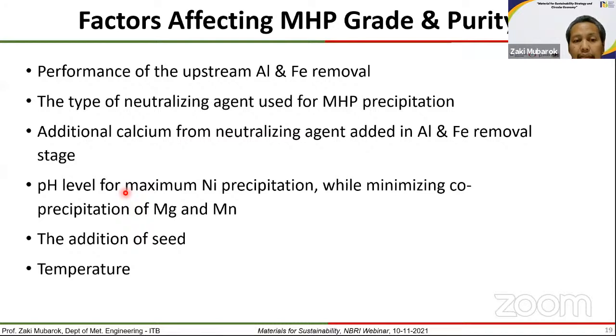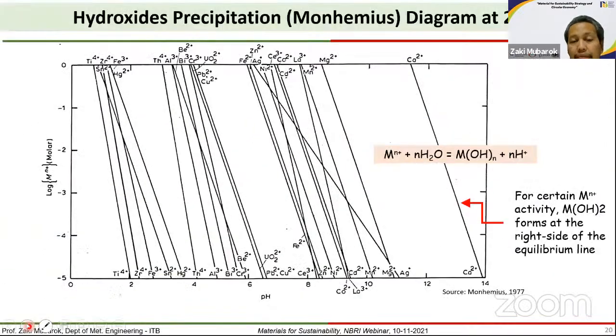Then the pH level for maximum nickel precipitation while minimizing co-precipitation of magnesium and manganese. So basically, magnesium and manganese are precipitated at quite high pH. But if you precipitate nickel at pH above 7, some of the magnesium and manganese are also co-precipitated. Then the addition of seed and temperatures, and I would like to share several of our investigation results.